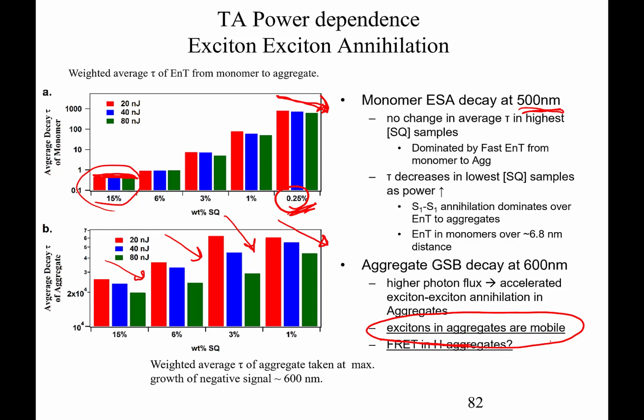And it suggests, again, that Förster resonance energy transfer in these H aggregates actually takes place, despite the fact that these aggregates we expect to have very, very low fluorescence. And so that's really astonishing, that there's so much energy transfer. It also tells us, therefore, that that's why we still actually get operating devices with these aggregates.